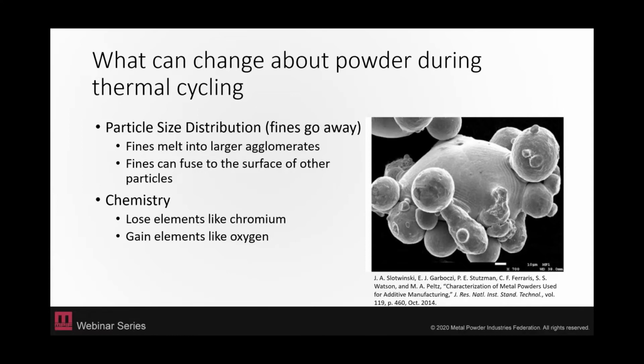We all know that as elements are heated, they are more reactive and basically they move around more easily. So in powder bed fusion, electron beam or laser, the powder gets heated anywhere from 400 degrees Celsius to 1,000, depending on what material you're building with. And that's not the melted part, that's the powder bed. And so there will be chemistry going on between the powder and the environment. So elements like oxygen can creep into the powder. We all know that metals don't want to be metal, they want to be oxides.